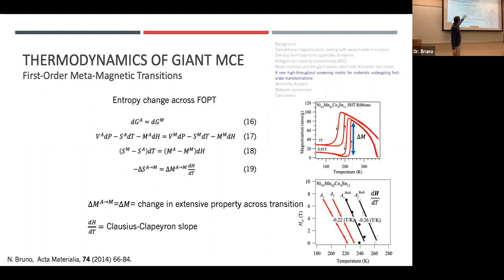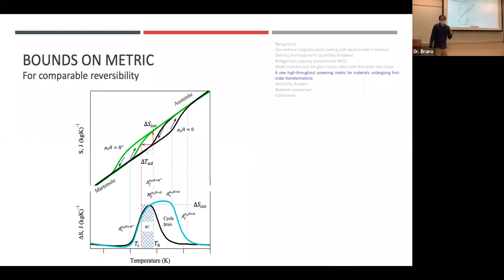And we can work through it and find what's called the Clausius-Clapeyron relationship. That's delta S, or entropy change from austenite to martensite, equals the magnetization change across the first order transition times dH/dT. dH/dT is the Clausius-Clapeyron slope. The way we find the Clausius-Clapeyron slope is by performing a whole bunch of thermal magnetization measurements under different fields, picking out our critical transformation temperatures and plotting those temperatures with applied field. The slope of those lines gives us our Clausius-Clapeyron slope. Okay. So it's a little different than just a ferromagnetic material.